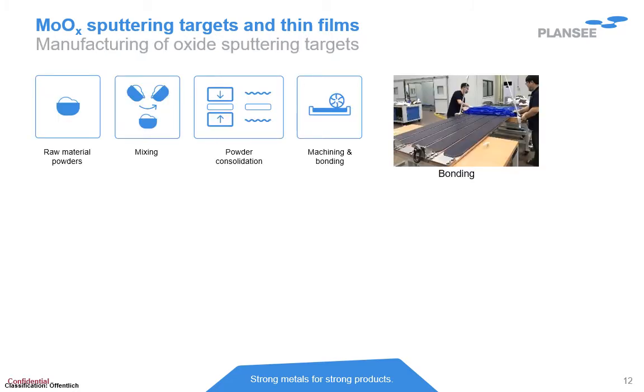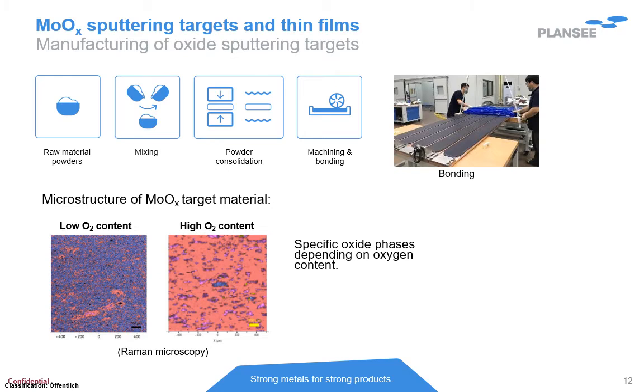Our production process for producing such molybdenum oxide sputtering targets is based on powder metallurgy. That means we are using different oxide powders, maybe also adding metal powders, mixing them, and using hot temperature powder consolidation to achieve high density and good microstructure of that material. In general, for most of the applications, those consolidated targets are then additionally machined and need to be solder bonded on a backing plate.